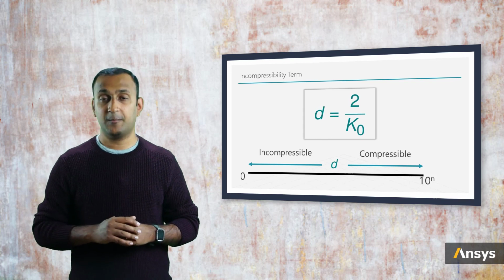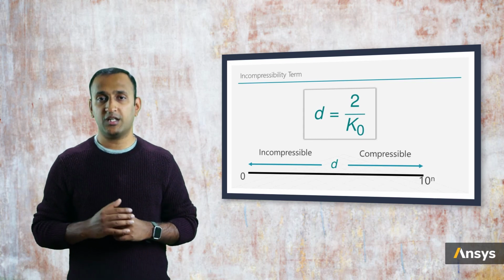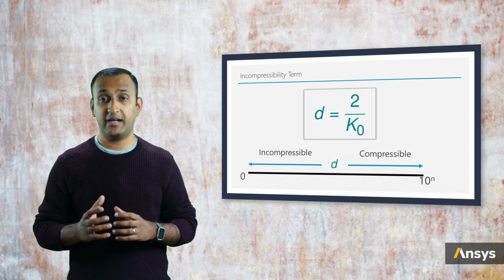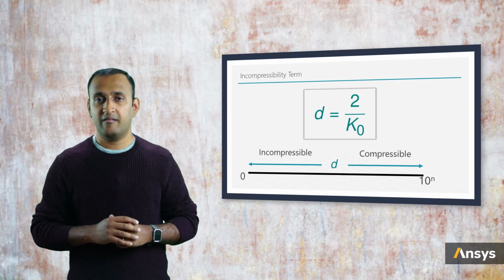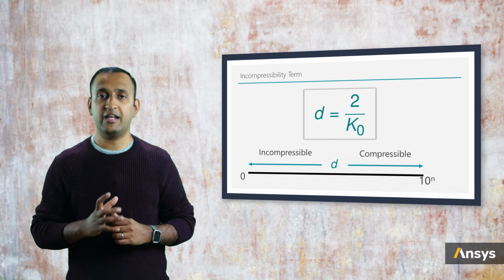In some cases, if we need to introduce a small amount of compressibility to make it nearly incompressible, we need to pick a very small value of D. One recommendation is to set the initial bulk modulus to a few orders of magnitude, about 100 to 1000 times higher than the initial shear modulus, and calculate the value of D accordingly.